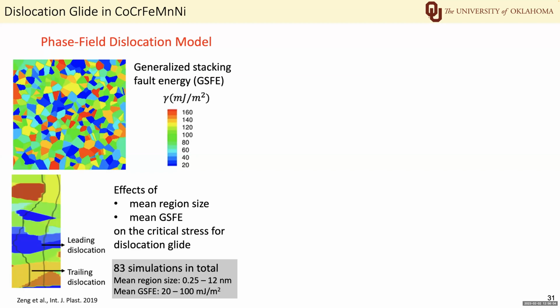By varying the mean region size and the mean GSFE, we carried out 83 phase field simulations. We found that both the region size and the GSFE affect the critical stress for the dislocation glide. However, we were not able to quantitatively understand those effects because there were so many inputs and outputs.